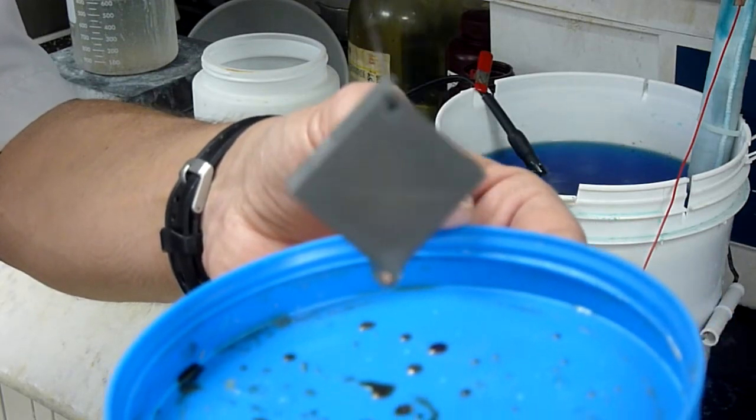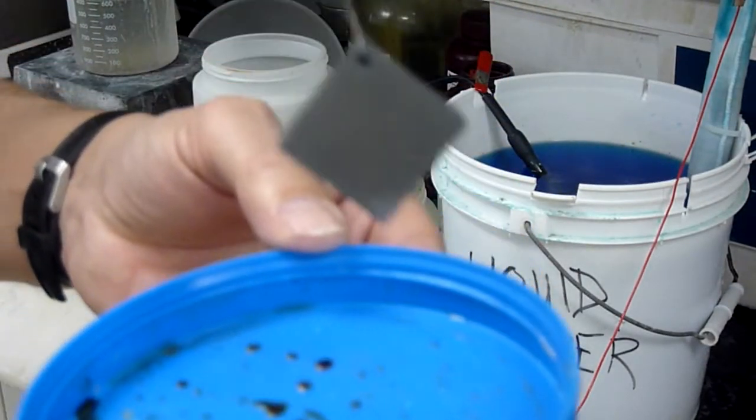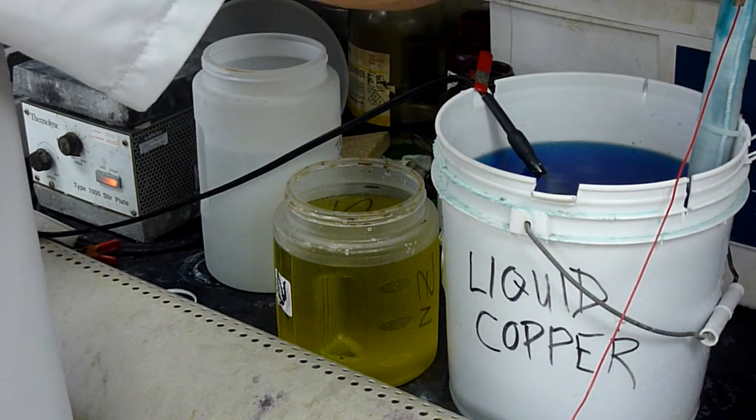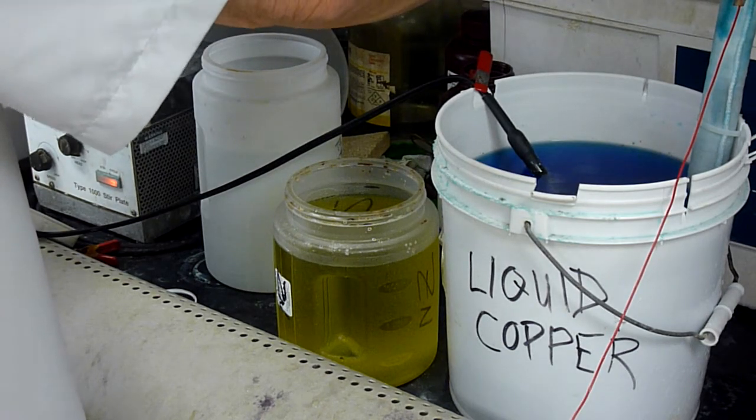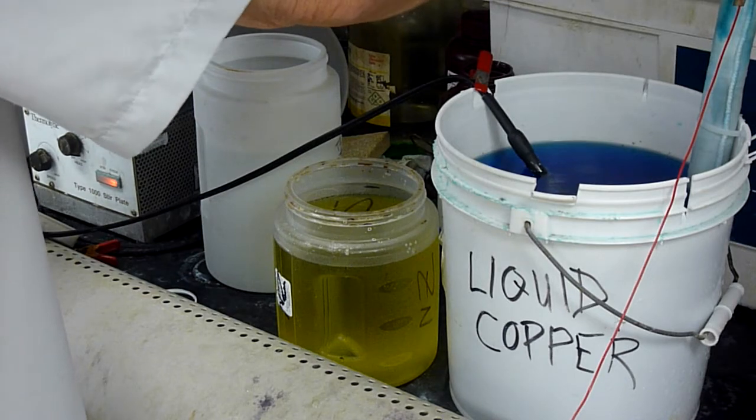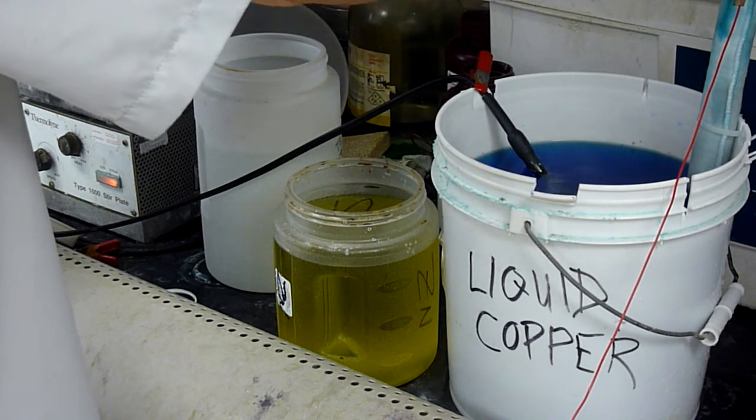That's our first layer of zincate. I'm going to give that a quick rinse. But we're going to double zincate this part. So even though it looks beautiful, we're going to take that off. We're going into nitric acid for a few seconds. The theory behind this is a little bit vague, but I think you can regard the first zincate as a bit of a cleaning step. This dip into nitric acid can be regarded as another cleaning step.